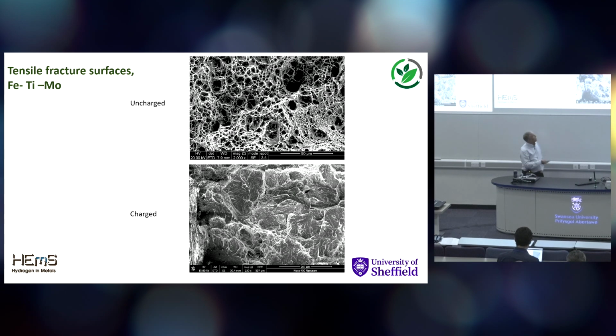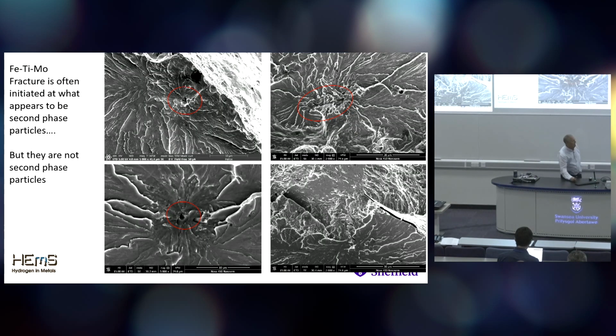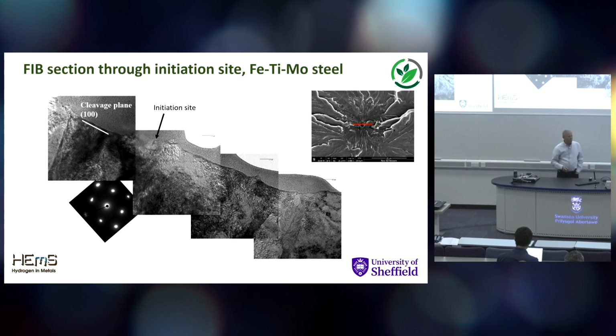Looking at the fracture surfaces, classical, top one uncharged, cup and cone fracture. Lower one here, we can see the cleavage nature of the fracture, classic hydrogen embrittlement. Going up in magnification at that, we can usually work out where the initiation site was. You can see these rather weird features here at the initiation sites, look like holes, and they're often attributed to things like manganese sulfide or some inclusion. But when you do a nice FIB section through, so in this case, we've got what appears to be a hole there, you take a section through it. So this is a cross section along there. This is that hole that you're looking at, which is the initiation site, and then this is the propagation away from that point.